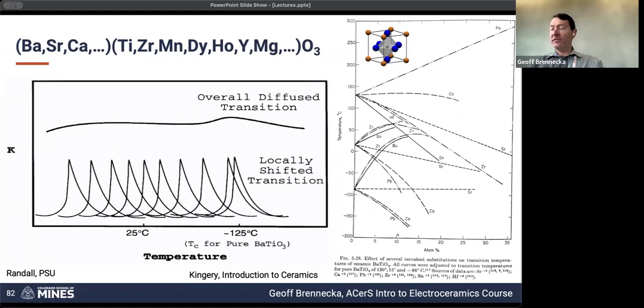So one thing that enabled this was a lot of foundational work looking at the effects of different alloying elements on the phase transitions within barium titanate. So I've put this classic plot on the right. This is the version that I took out of the Jaffe cookbook, showing the effects of different alloying elements. So if you replace barium with lead, then the temperature of the tetragonal to cubic phase transition goes up significantly. If you replace it with calcium, it doesn't change a heck of a lot. If you add strontium, then that phase transition decreases significantly.